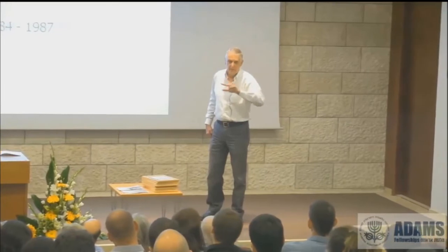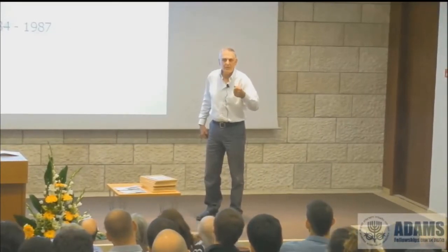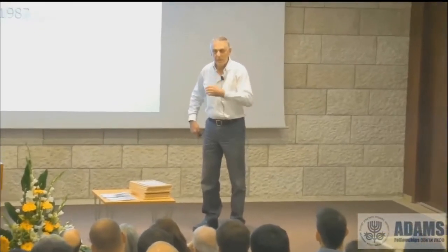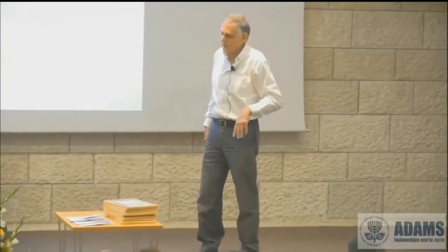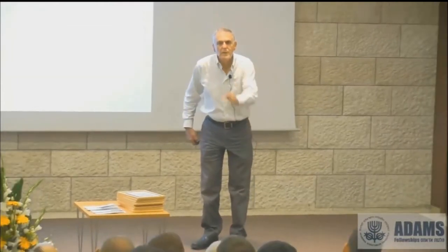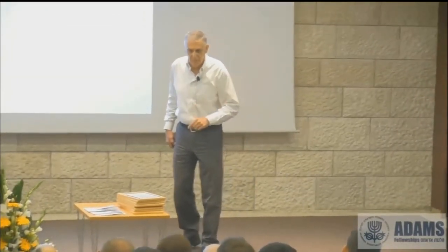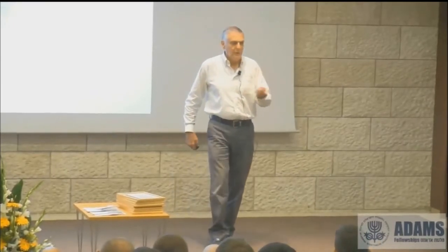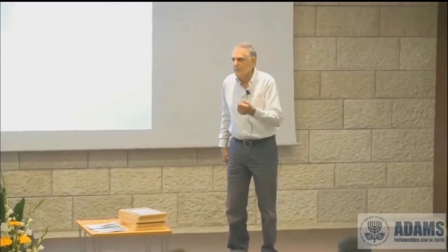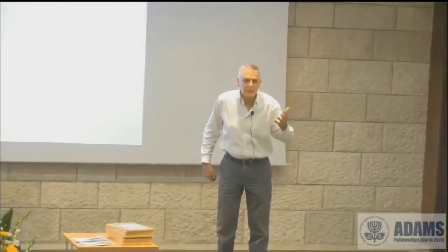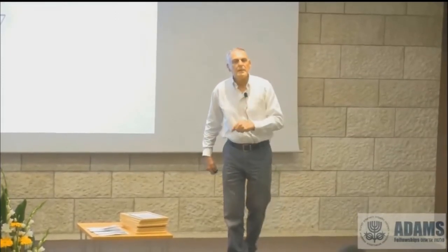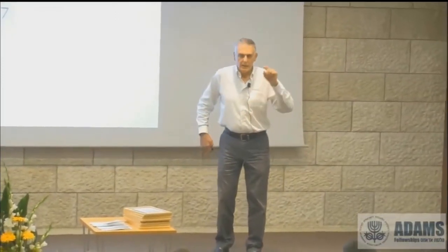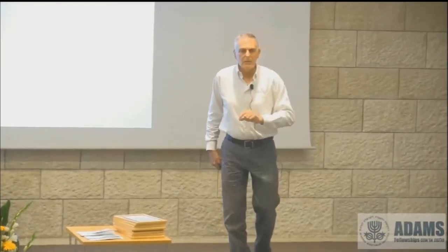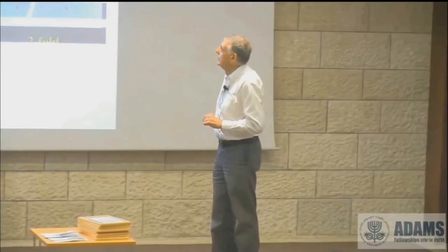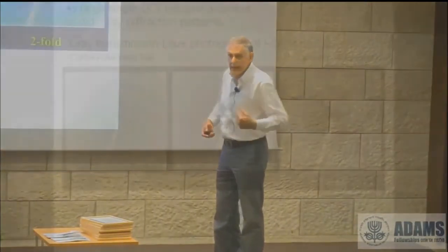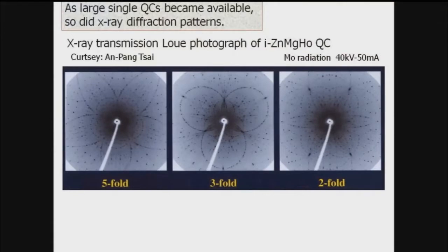They were very wrong, of course, because electron microscopy is a fantastic crystallographic tool, especially nowadays. But they wanted X-ray diffraction. We could not give them X-ray diffraction because our crystals were very small, 1 micron inside. And in order to have a diffraction pattern for one quasi-periodic crystal, you need a crystal to be about maybe a tenth of a millimeter, that's good enough. We didn't have that. But in 1987, my colleagues in France and in Japan succeeded in growing large enough crystals for X-ray diffraction.